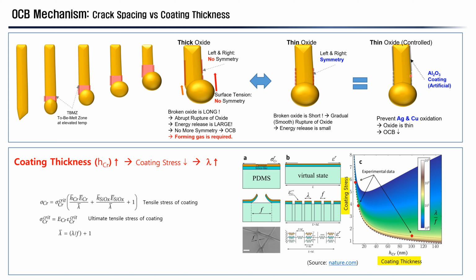As a result, you can control the OCB formation. At the bottom, you are seeing a typical mud crack of a very thin coating. Here, this particular paper describes the stresses in a coating layer as a function of coating thickness.